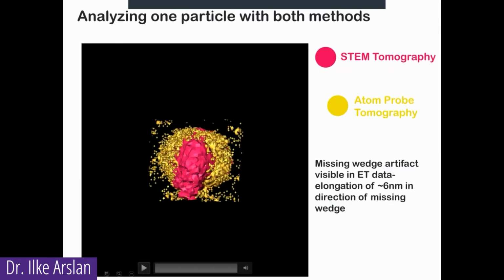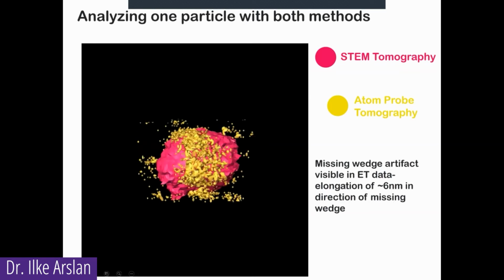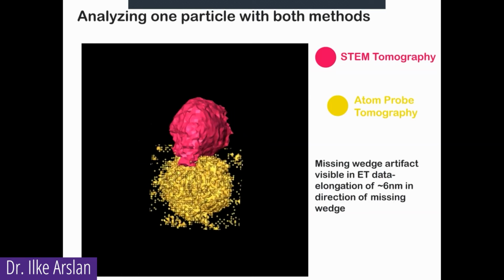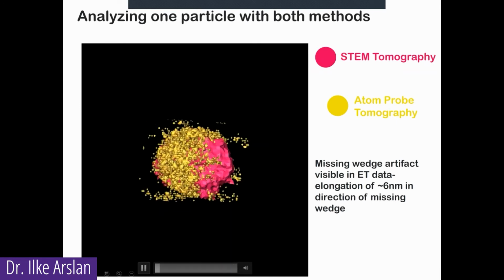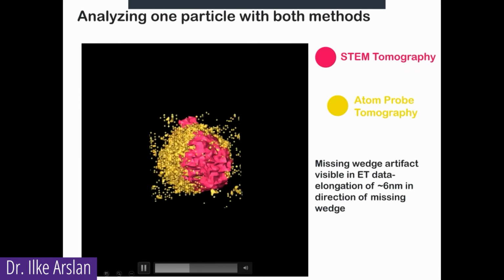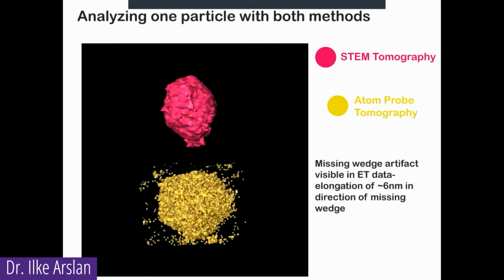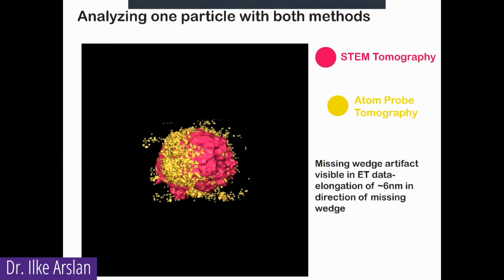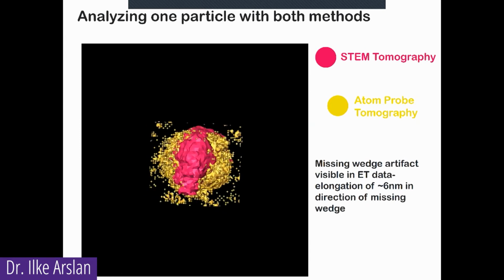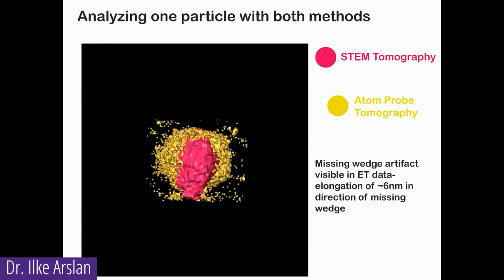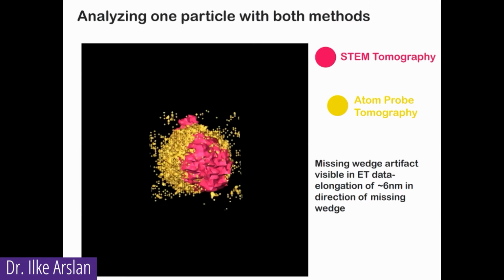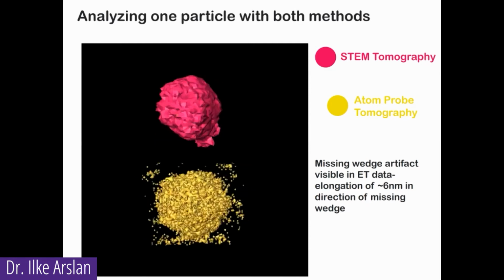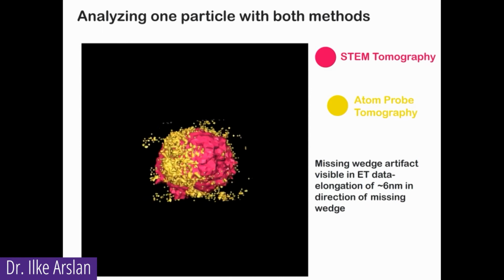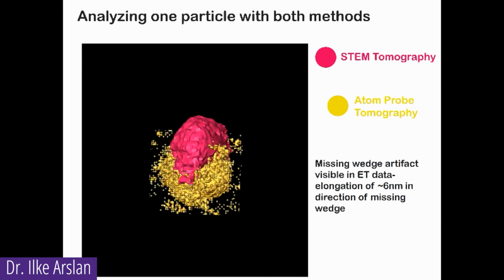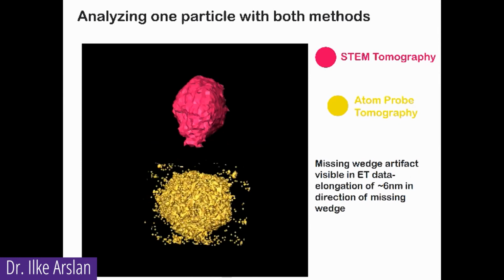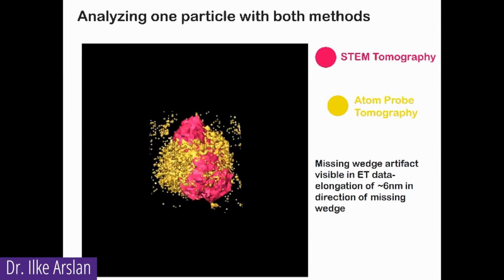Okay, so in this movie, you can see that the artifact from the electron tomography is the missing wedge. That makes the particle 6 nanometers more elongated than it should be. So the combination of these two techniques is really powerful because they have artifacts in exactly perpendicular directions. They're orthogonal to each other, so you can get accurate information if you're lucky enough to get it to survive in both an electron tomography and an atom probe tomography. So it takes some work, but I think the atom probe field has also been moving in the direction of doing at least some TEM, because that really helps with the artifacts in the atom probe tomography.